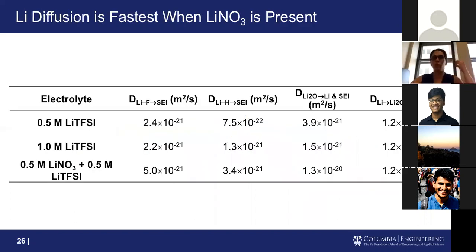So what are these actual diffusion coefficients? What we see here is the individual diffusion coefficients for lithium fluoride going to other places in the SEI and so on. This is sort of a lot of data, but just to summarize, the most important part here is that lithium atoms moving to the passivating lithium oxide layer all have the same exact diffusion coefficient. So that dynamic process at that electrode-SEI interface is not changing whenever we change our electrolyte. What seems to actually be changing the most is the layer above that, when you're going from lithium oxide to the rest of the SEI.